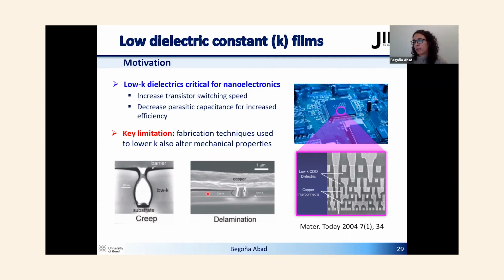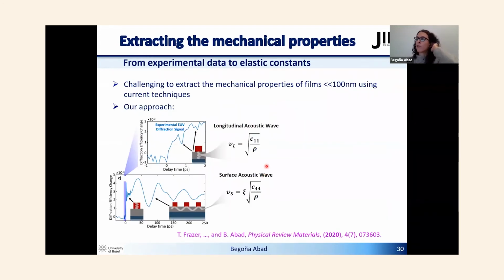So for example, we can get some delamination or creep. This is really challenging because we need to find a compromise between good mechanical properties and still good dielectric constant. So this is the motivation for us to measure the mechanical properties of extremely thin low dielectric constant films. And how do we do that?